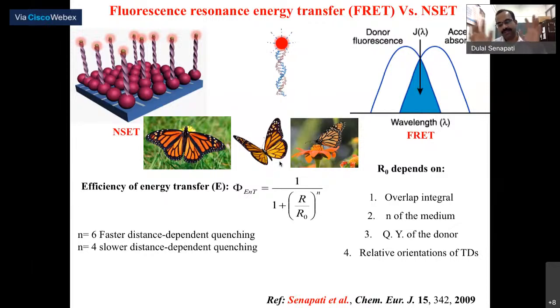The difference between the organic fluorophore-based donor-acceptor and the nanoparticle-based one is that for the organic one, the donor and acceptor are kind of like point vectors. So only when the vectors are parallel to each other is the energy transfer maximum. But for nanoparticles, suppose this is a sphere, they don't have a specific vectorial direction. So in any direction of the donor, it can transfer its energy. So the energy transfer efficiency is much higher in nanoparticle-based donor-acceptor pairs.